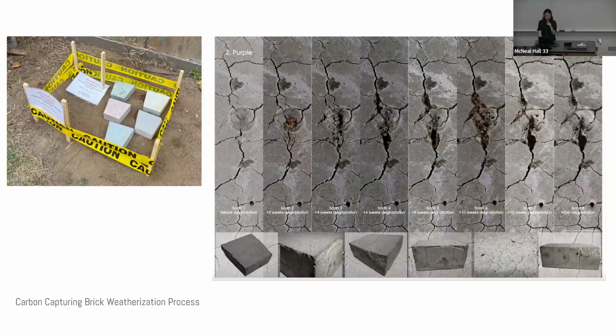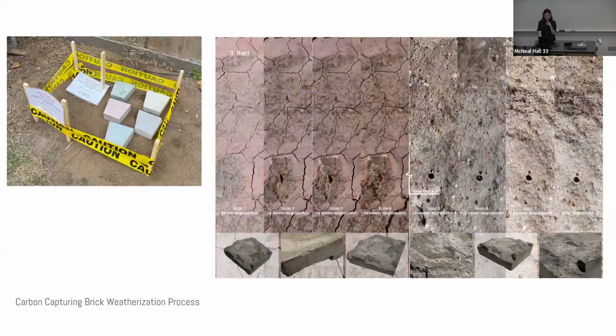This one is a purple brick, and every brick has Portland cement as its basis, and this one has biochar and plaster and CaO. This one is a red one, has cement, CaO, and plaster. And you can see that on this one, there was a drastic change after week 4, which is when the surface completely fell off and started to crumble.